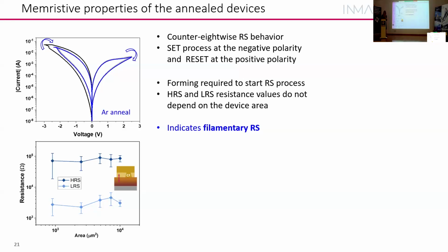So now we have less oxygen in our material, and we try to do the switching. And what we obtain is a filamentary switching. So we have, as I showed before for the pristine devices, a forming step, and we have two high and low resistance states that are the same independent of the area.